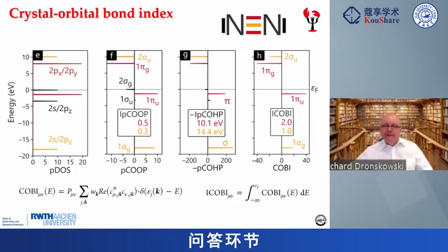Oh, it's very simple. We did this in the paper. So sodium to helium is very different. I don't have a slide here, but I can tell you. When you squeeze sodium to helium, the pressure becomes so large that you squeeze the electrons out of sodium. So you have sodium plus. And these two electrons go into empty sites.